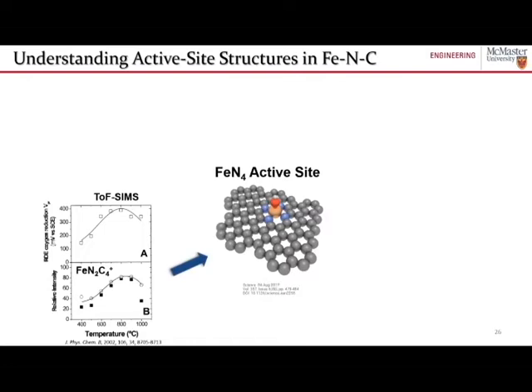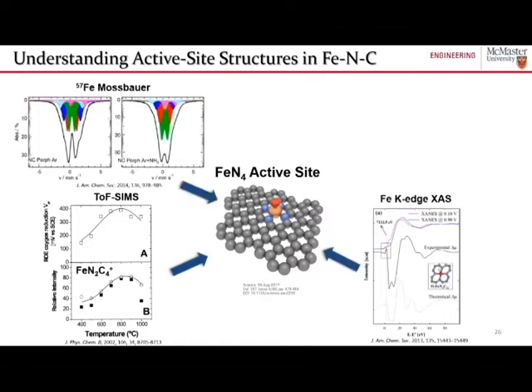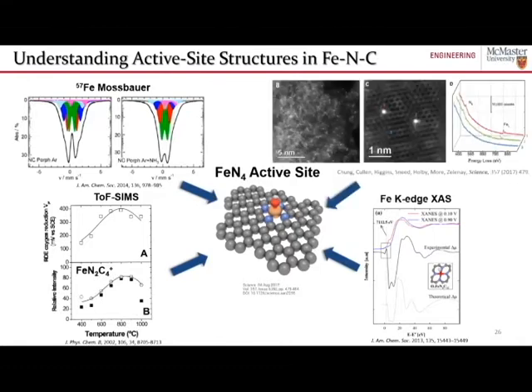There's been a lot of follow-up studies using different techniques like Mossbauer spectroscopy, X-ray absorption spectroscopy. And more recently, I was part of a study when I was at the Los Alamos National Lab. We were able to use STEM imaging to observe these bright spots that we hypothesized to be single atom active site structures. But a key thing that I want to mention is there's a lot of papers that do that. They do this high resolution microscopy, see bright spots, and immediately attribute that to these catalytically active metal ion centers.